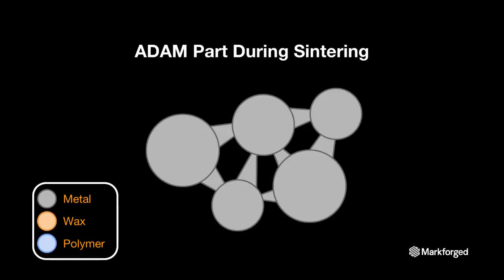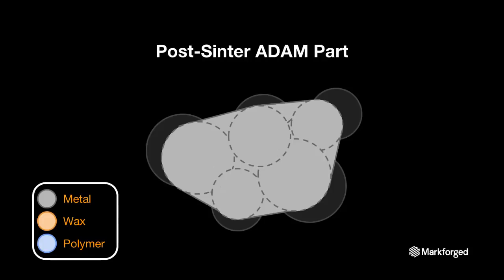And then the atomic diffusion part of the ADAM process happens during the sintering, where you're never melting these metals. It's about 85% of the melt temperature of the underlying metal. But the particles diffuse together, and your part shrinks down and forms a solid part, as you see right here, formerly composed of those small metal powders.